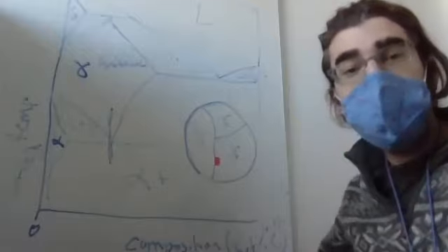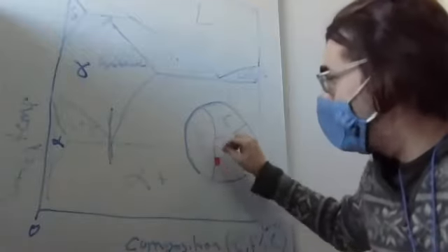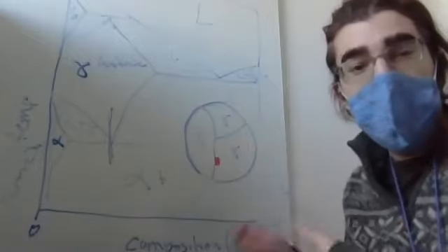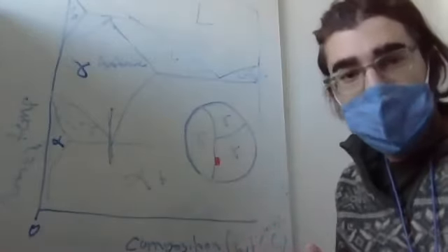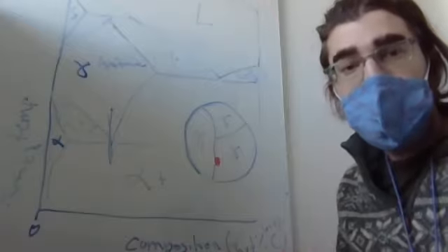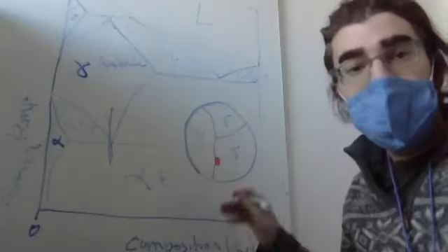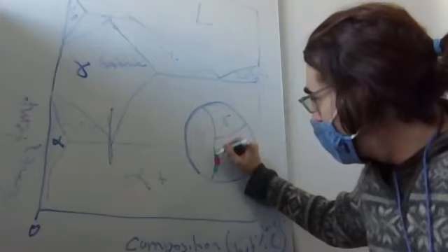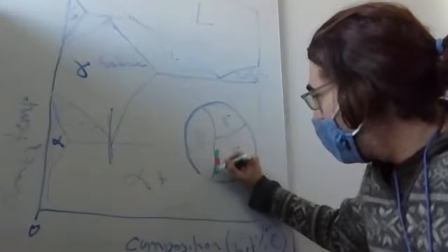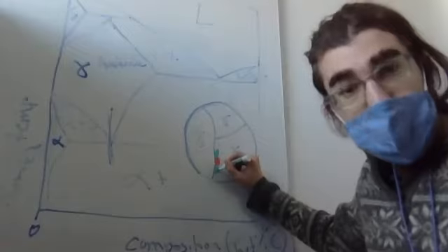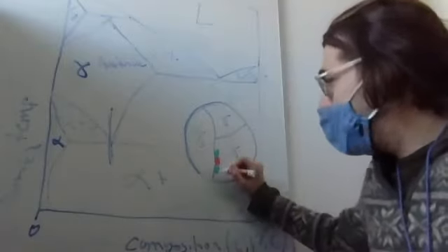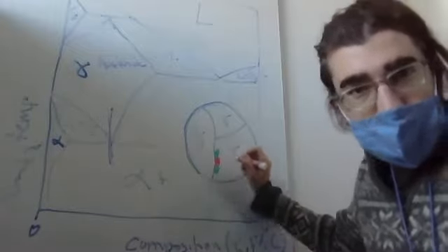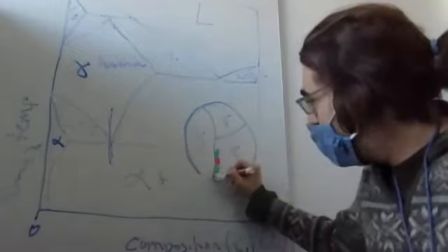And then carbon will begin to migrate to this region. So you have a lot of carbon here and it's going to attract more carbon. So then around the cementite phase that's forming, you're going to have a carbon deficient region, right? Because all the carbon is going to this red spot. So then you're going to get this green spot here, right? Of a carbon deficient region. And then any carbon that is in this carbon deficient region is kind of like, well, why am I sticking around here? And then you'll get another red spot down here.